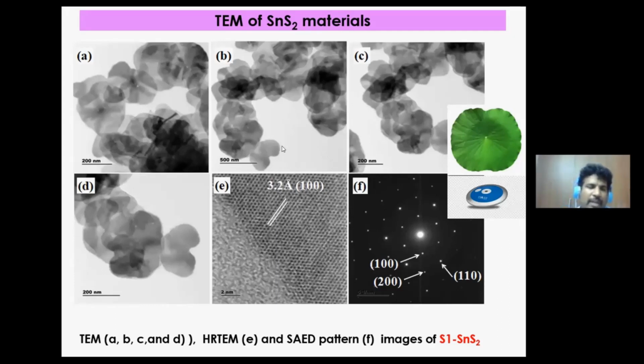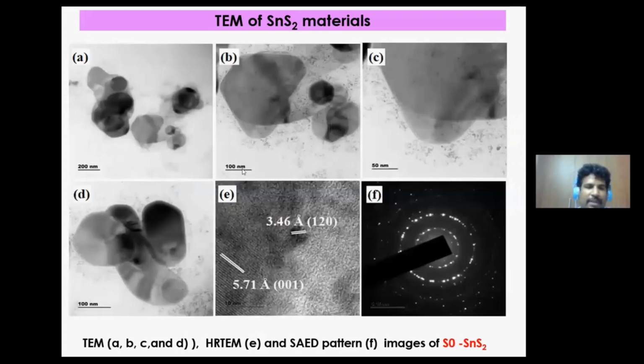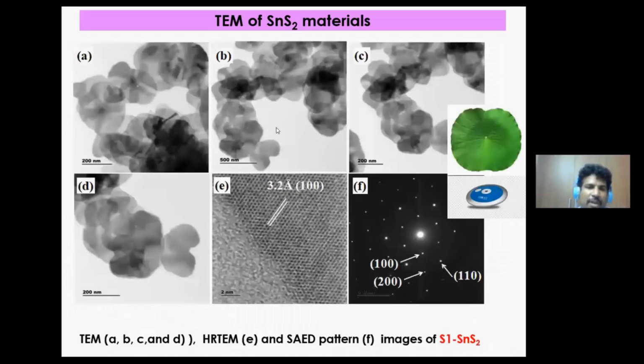Once you introduce oleic acid and octadecene, the growth of tin disulfide is completely controlled, and also the structure is somewhat definable. In the previous case, we couldn't define the structure, and once oleic acid is introduced, we got a controlled structure. Here, the really beautiful HRTEM image shows the 100 plane of SnS2. With the SAED patterns, we got very beautiful spots. With those spots you can define the planes. That is the X-ray spots viewed from the top.